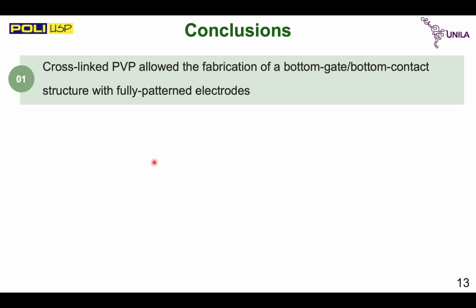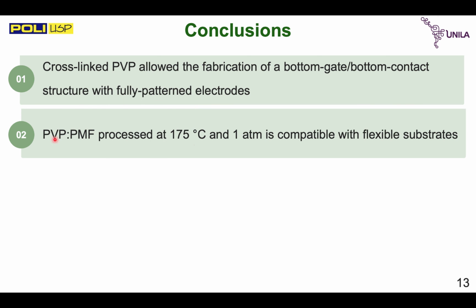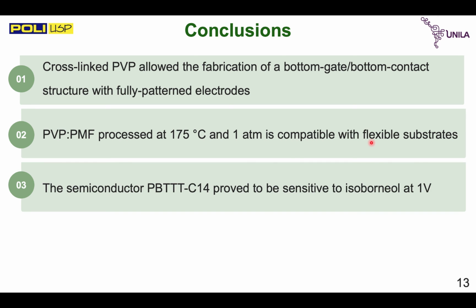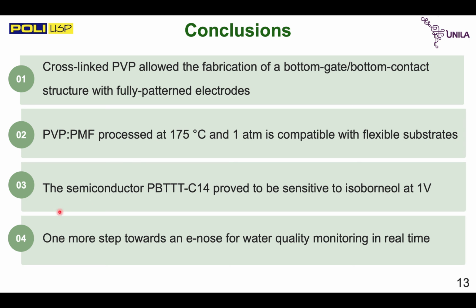Okay, so now the final conclusions. Cross-linked PVP made it possible to fabricate bottom gate, bottom contact transistors with fully photopatterned electrodes. The cross-linked dielectric was processed at 175 degrees Celsius and 1 atm, which is compatible with some flexible substrates. The semiconductor, both in chemical sensors and transistors, proved to be sensitive to isoborneol at 1 volt, which is really a low voltage for organic devices.